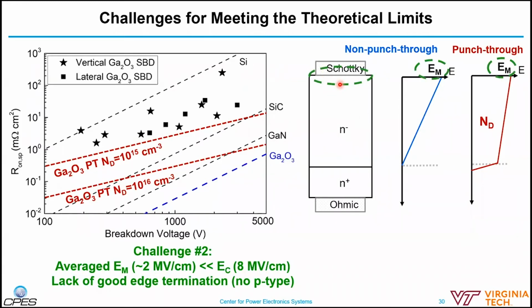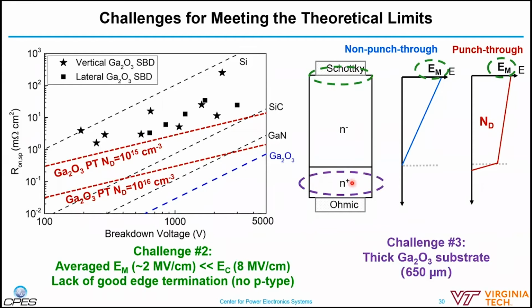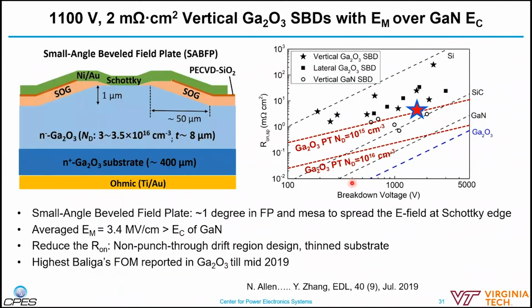And also the challenges about electric field management. In real devices, the peak electric field is typically much smaller than the critical electric field of gallium oxide. And also the substrate typically has a very large resistance. So two years ago, in 2019, we demonstrated a vertical gallium oxide Schottky barrier diode by combining several different design considerations. For example, we use a non-punch-through design with a relatively high doping concentration in the drift region, and we made a new field plate design, which has a very small bevel field plate, essentially allowing the spreading of the electric field.